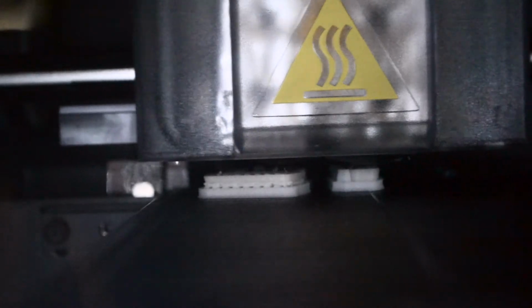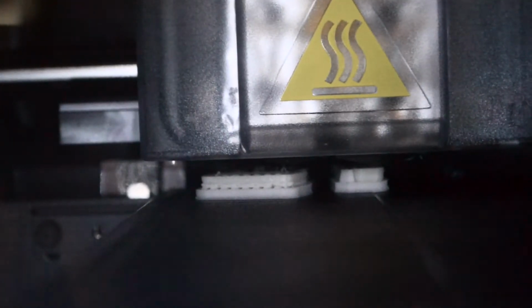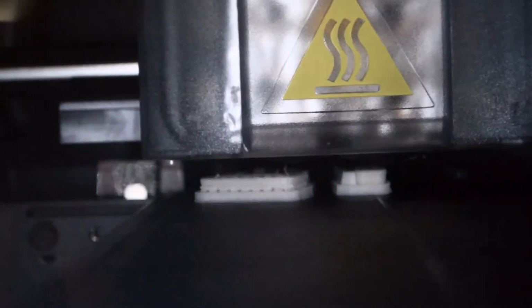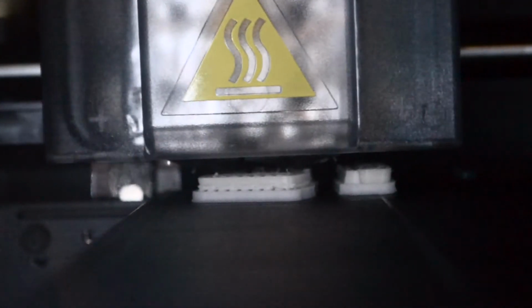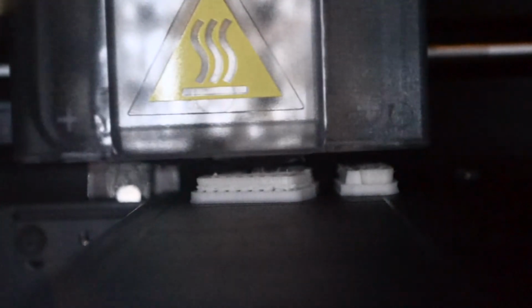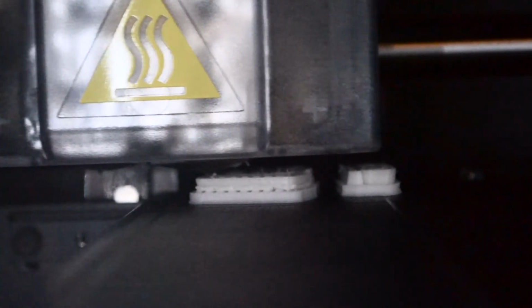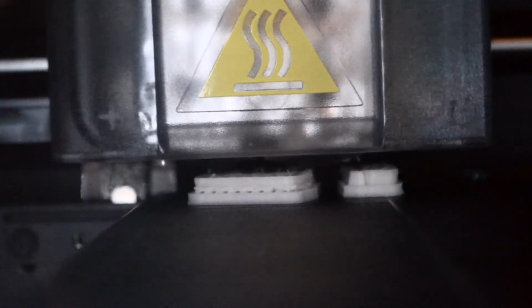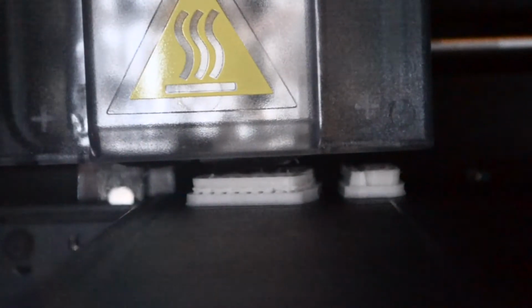Once the job is sent to the machine, it begins printing, laying down layer after layer of model material, building parts from the bottom up. Overhangs, undercuts, and holes are all supported by a dissolvable support material, allowing us to produce the most complex geometry which wouldn't otherwise be possible. After each layer has been printed, the build tray moves down by 0.25 mm, and the next layer is laid down on top, simultaneously printing model and support material.